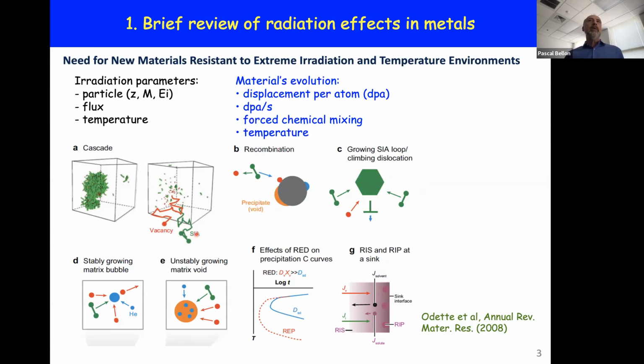There is also a metric or measure of the damage under radiation. A displacement is one pair of vacancy and self-interstitial, and the measure of the damage would be whenever you have created one pair for each atom in the material. So 1 dpa is a very high level of damage already. It means you have created on every lattice site a vacancy or an interstitial during the duration of the irradiation. The irradiation rate or damage rate, dpa per second, is also important, as we'll see. In addition to creating damage, irradiation also creates forced chemical mixing during this very energetic displacement cascade.